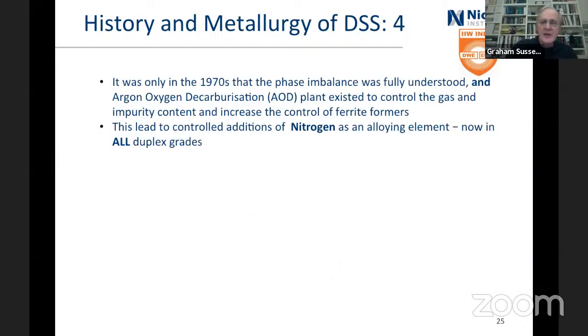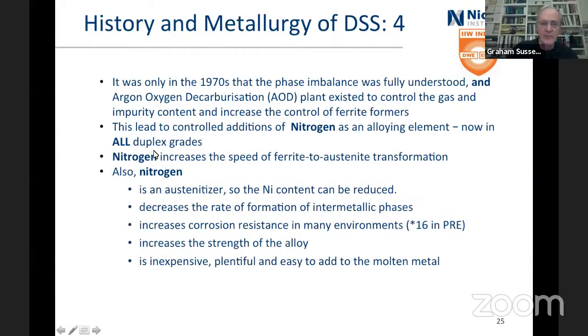Okay, so in the 1970s, the phase imbalance was fully understood, and argon oxygen decarburization, the AOD that everybody uses now, was designed and was being taken up by everybody. So the impurity content could be controlled, and you got decent control of the ferrite formers. That led to controlled additions of nitrogen, and so nitrogen is now in all duplex grades, absolutely all of them.